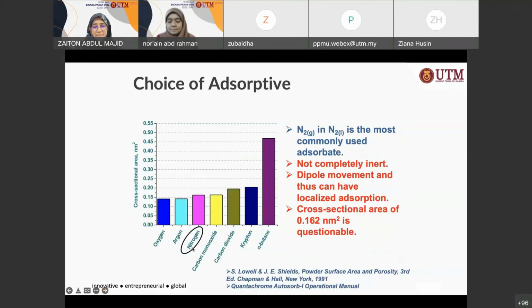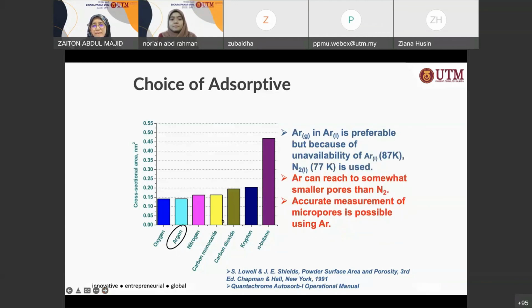Okay. Most of the time, because I missed this slide just now, nitrogen is the most common adsorbate used. They are not completely inert, right? They have a dipole moment and thus can have localized adsorption. Because when we talk about physisorption, our assumption is that the adsorption is localized. So one of the reasons why we choose nitrogen is that it can have a localized adsorption. Even though it may not be completely inert, this is the best choice, the cheapest choice, and it also has this localized adsorption. And argon, as we said, for micropores for example, you can take argon or krypton or carbon dioxide. Other than that, you might want to do a t-plot or play around with your sample size, and so on.